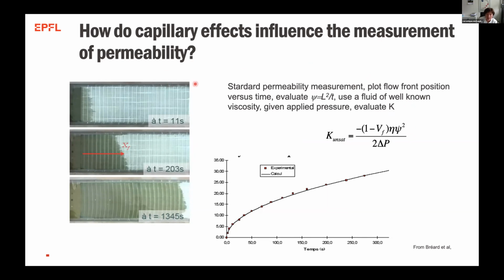And in permeability, measurement of permeability, this is something that people have been discussing a lot. And I stole those from my colleague Joël Brea because I was too lazy to take hours. But you see, you measure the flow front progression. What you do is that you use a fluid with a well-known viscosity, like silicone oil or whatever. You apply a constant pressure, and then you plot what is the flow front position versus time, and then you can find the permeability, which would be linked to this psi square, which is the slope of L square over time, which should be linear, and then you divide by delta P.